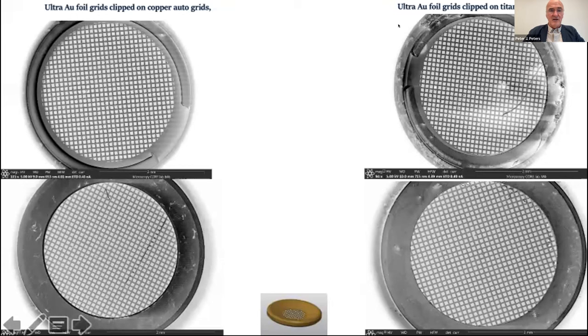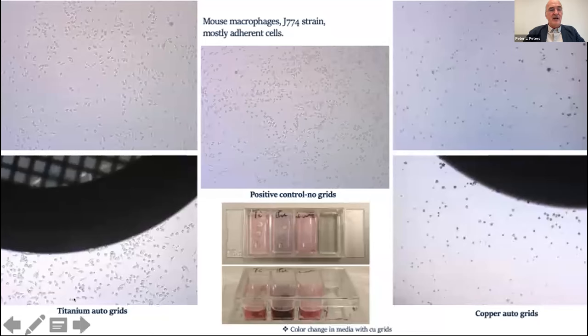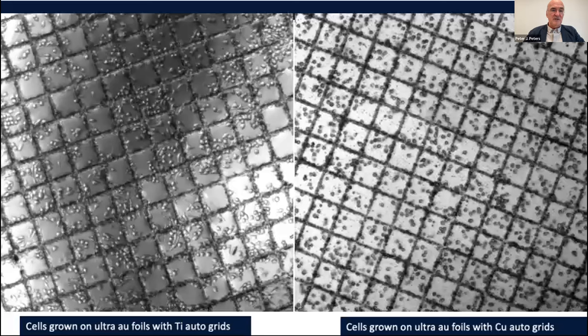So we like to use now gold grids that have titanium outer grids, and we made them here nearby in a workshop, and they work exactly like you see here. And we grow cells overnight on titanium, which is also used in the body, for surgery in the bone. And we compare the titanium outer grids with copper grids. And in copper grids overnight, all cells die. You can see here the dead cells have a different color. And with titanium, all cells are happily growing overnight. And so this is a much better way to start the procedure of making cryo-electron tomography by vitrifying these. Here you can see cells that grow on the titanium versus copper. Here they are dead and here they're happy. So we are aiming for these cells.